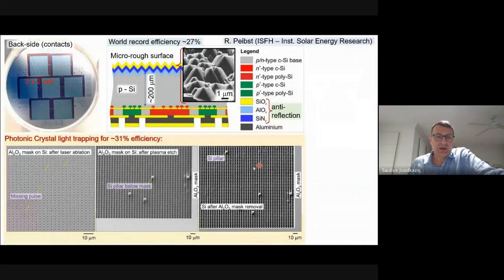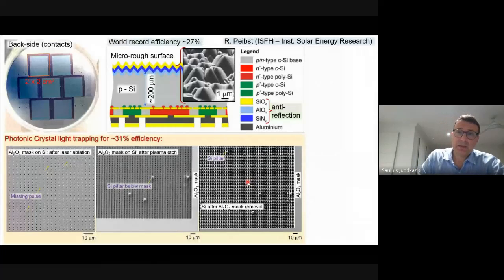So this was done on real solar cells. Instead of chromium, we started to use an alumina mask, which is dielectric, and it's better for surface recombination of optically created carriers in the solar cell. And alumina is always part of the anti-reflection coating on solar cells. So we use this as a mask. We ablate it, do the next step of plasma etching, and then remove the mask to have the periodic structure.